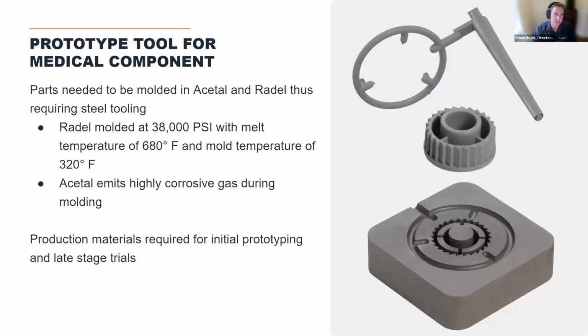So the parts here needed to be molded in acetal and Radel, so they could not have been molded in an aluminum tool like a lot of people would have liked to during that prototyping stage. Radel was molded at 38,000 PSI, had a high melt temperature, and the mold was actually heated as well. Acetal was emitting a corrosive gas during molding, which would have made aluminum not acceptable.